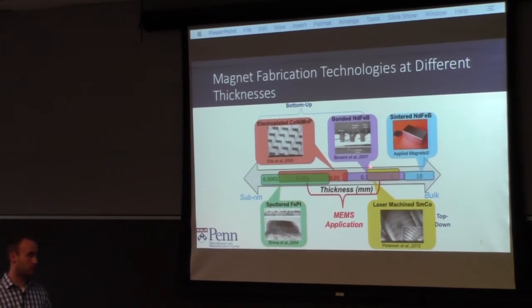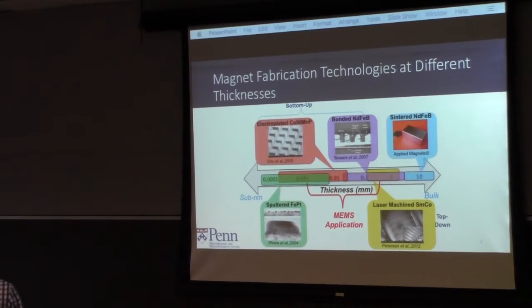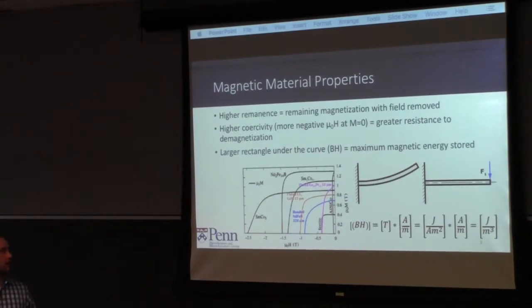They do share the same space with that bonded NDFEB, but the bonded have a couple of downfalls. First, the magnetic properties are nowhere near as good as the samarium cobalt, as a sintered metal. Secondly, they're usually only magnetized in a single direction. When they're not, they're magnetized first in a single direction and then reverse magnetized the opposite direction, so you lose some field in either case.